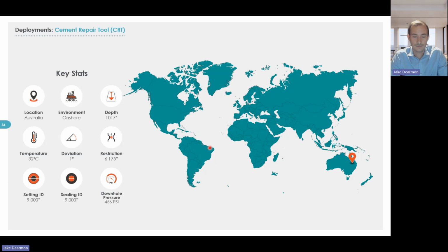Traditionally, the methods to remediate that would either be a bleed and lube method from surface or a squeeze cement job. So what we're doing with the BiSN alloy is essentially similar to a squeeze cement job, where we're going in and perforating or somehow gaining access to the annulus at depth. We then go in with a BiSN tool and melt the alloy through those perforations into the backside, flowing through